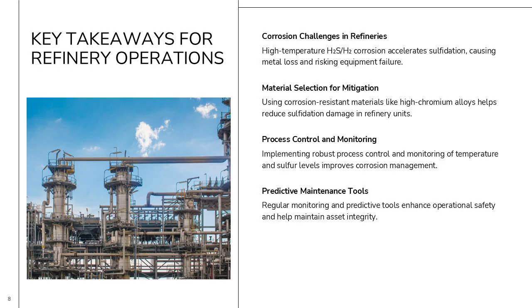High-temperature H₂S/H₂ corrosion is a critical issue in refining and petrochemical industries, particularly in hydroprocessing units operating above 400 degrees Fahrenheit, 204 degrees Celsius. The combined presence of sulfur compounds and hydrogen creates an environment that accelerates sulfidation, leading to uniform metal loss and potential equipment failure. Effective mitigation requires selecting corrosion-resistant materials, such as high chromium alloys, and implementing robust process control measures to manage temperature and sulfur levels. Regular monitoring and predictive tools further enhance corrosion management, ensuring operational safety and reliability. By understanding the mechanisms, sources, and preventive strategies, refineries can minimize the risks associated with sulfidation and maintain the integrity of their assets.